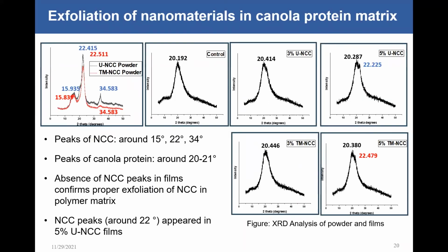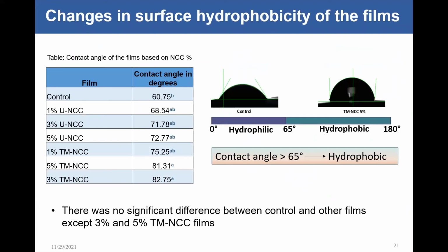We did the X-ray diffraction to identify the exfoliation of the nanomaterials. So I'm not going to go into too much detail about it, but what we basically observed with the X-ray diffraction is the exfoliation of nanomaterials is pretty good, almost up to 5% in the TEMPO modified nanomaterials. But with unmodified nanomaterials, at the 5% level, there is a slight aggregation of the nanomaterials, but after you modify it, it's much better in terms of the exfoliation.